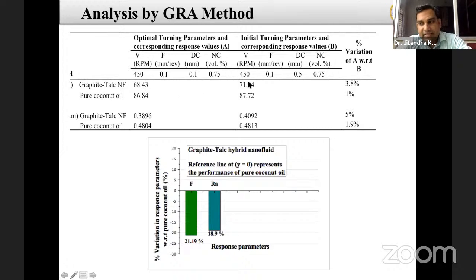And further, because this is the Taguchi method, and this 4x3 is most probably an L9 experiment, I select another set through the manual way. Okay, we perform 450, 0.1, 0.5. This is the confirmation test. We compare the optimized data we obtained with the confirmation test, and we observe that the variation is between 1 to 5%, which is the permissible limit of acceptability. In the case of surface roughness also, it does not vary that much, even though we increase the depth of cut from 0.1 to 0.5.